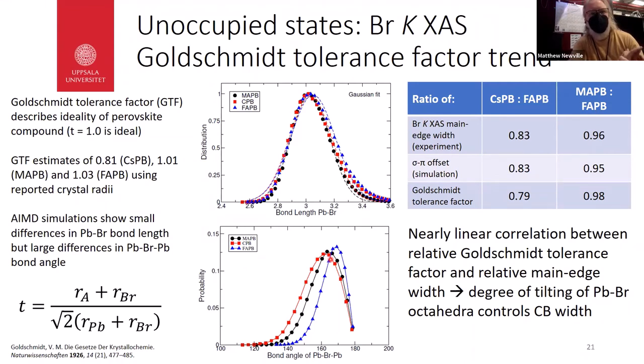Yeah, I think for cesium lead bromide, the ionic radius of cesium is quite a bit smaller than what it's supposed to be for an ideal perovskite compound. And so that probably affects, I guess, the lead bromide octahedra, which have to tilt to try to accommodate the smaller A-site cation. Right, okay. I have some speculations about why this structure-only descriptor shows this linear correlation with the electronic structure, but they're just hypotheses at the moment. Okay. So great. Thanks. Very interesting stuff. Thank you. Selena, you have a question?